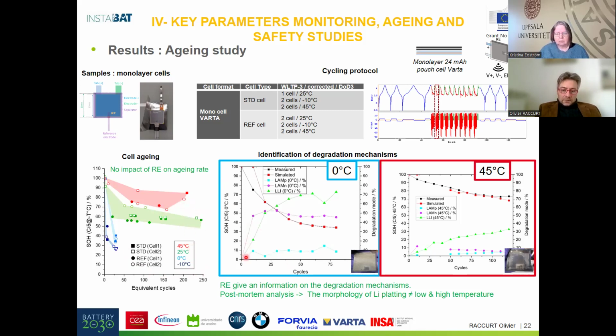And we can analyze, by using the reference electrodes, the loss of active material at the positive and negative side, and the loss of active lithium material, lithium inventory, sorry. And we show a difference between the behavior at 0 degrees and 45 degrees. For example, at 0 degrees, there is a lot of loss of lithium inventory during aging, but also a lot of loss of active material at the negative side. It is the purple curves. But at 45 degrees, the degradation is driven essentially by the loss of active lithium inventory, not by the loss of active material at the positive and negative side.